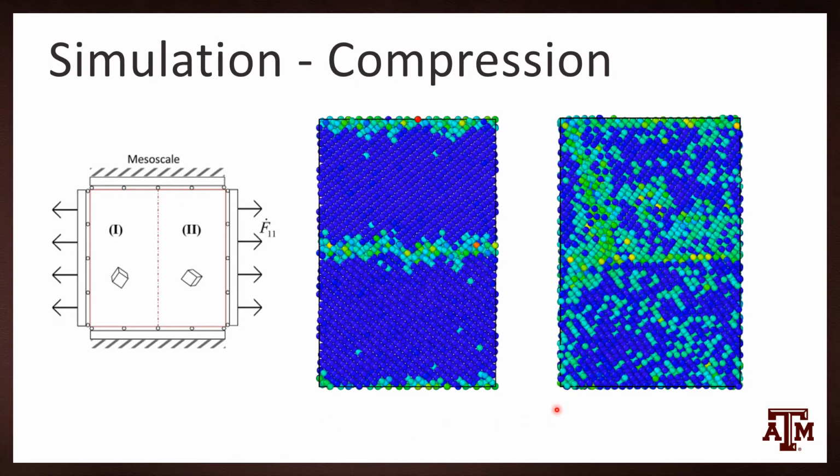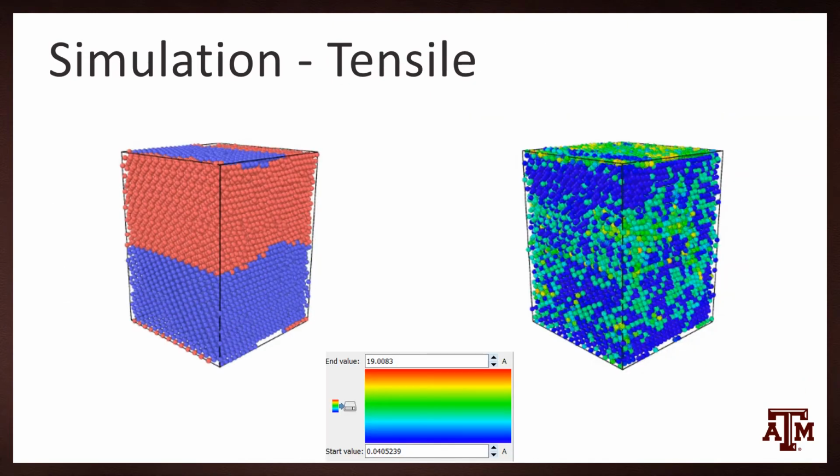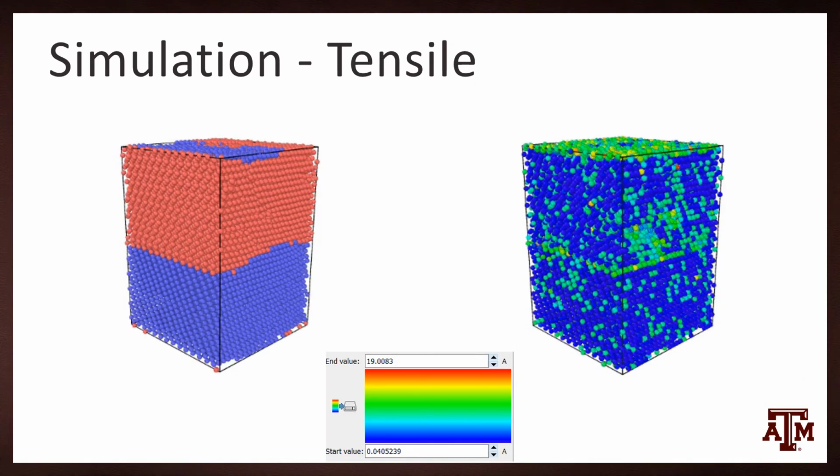The grain on the right is after compressing to 40 gigapascals and then pulling in tension back to the initial position. In addition to the grain boundaries, there is now a dislocation running diagonally in the top left, as well as smaller defects throughout. This shows the comparison between running the simulation with and without pre-compression. The tensile portion is the bulk of the simulation.